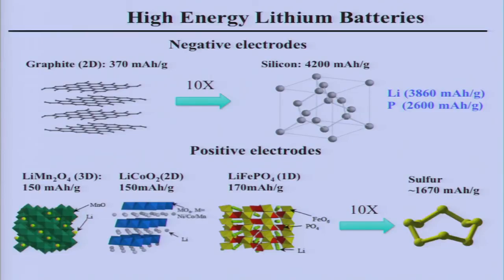The traditional positive electrode is the host: lithium manganese oxide spinel, lithium cobalt oxide layered structure, which is in your cell phone, and lithium iron phosphate. To get to 10x, there are also choices. A material like sulfur is very low cost and everywhere, a side product of petroleum refining. So we have those very nice materials, but it has not happened yet that we could use them for our batteries.